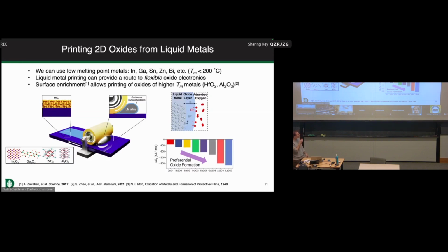So the exciting thing that I think gives us a really a large range of interesting things to study for years to come is that you can change that alloy composition. You can synthesize not just semiconductors and conductors, but also interesting materials that are based on refractory metals like hafnia, for example, or zirconia. So normally you wouldn't imagine that you could put those into a low melting temperature alloy, but it turns out that thermodynamics helps us in this case, that a lot of the refractory metals also have a much larger free energy of oxidation.